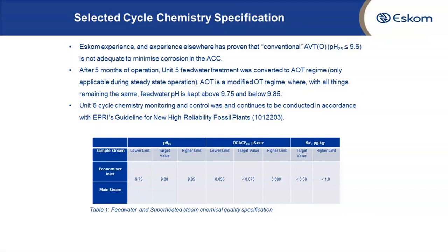After 5 months of operation, Unit 5 feed water treatment was converted to alkaline oxygenated treatment regime. And this is the regime that we adopt for all units once the circuits are cleaner, the units are stable, as well as the cycle chemistry has improved, then we transition to alkaline oxygenated treatment. Basically, this is a modified version of the oxygenated treatment, in Eskom terms, again, I have to indicate that.